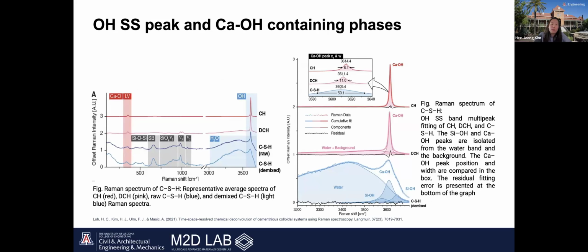So OH bonds can be found in many different components of cementitious materials. Here are the OH profiles of calcium hydroxide and the disordered calcium hydroxide. And lastly, CSH, which is calcium silicate hydrate, is compared. Both CH and CSH contain OH bonds, but their Raman peak position and peak width are different, reflecting their unique chemical environments. By decomposing the peak profiles, we can identify the local environments of the OH bonds and gain insights into the structural differences between these hydrated phases.